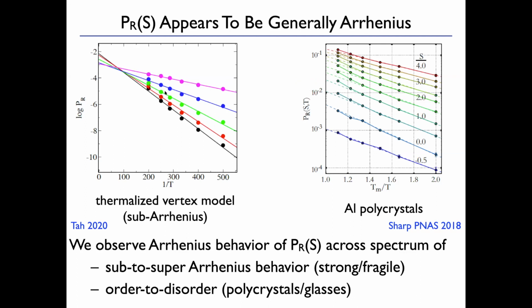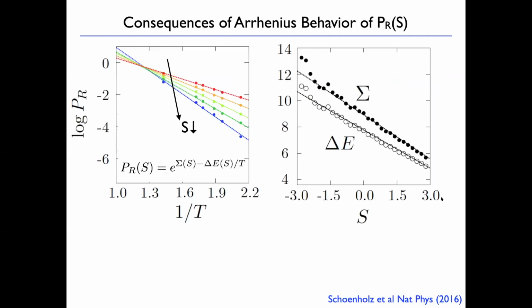We've looked at simulations of the thermalized vertex model of epithelial tissues. It's interesting from this point of view because it shows sub-Arrhenius behavior, so it increases slower than Arrhenius. In that case, again, we see the probability of rearranging is Arrhenius for particles of a given softness. And even crystalline systems, such as aluminum polycrystals: we can look at the probability of rearranging as a function of softness. It turns out soft particles live in grain boundaries and dislocations, as you would expect, and the probability of rearranging is, again, Arrhenius in temperature. So we see this Arrhenius behavior of the probability of rearranging across the whole range from sub-Arrhenius to Arrhenius to super-Arrhenius behavior, the range of fragile to strong glasses, and across the whole range of order to disorder, crystalline to glassy. And of course, the whole softness idea works across these ranges as well.